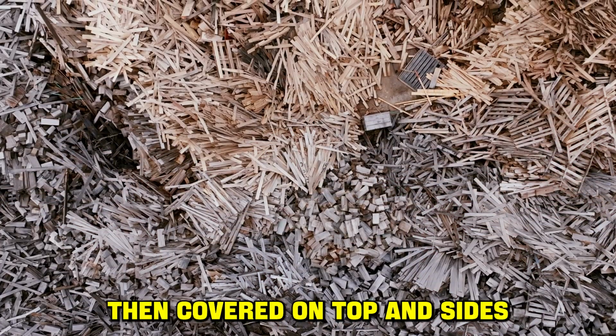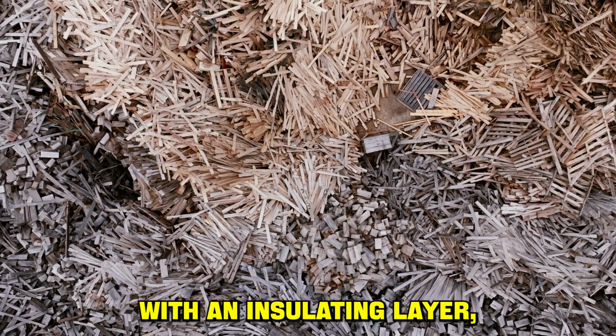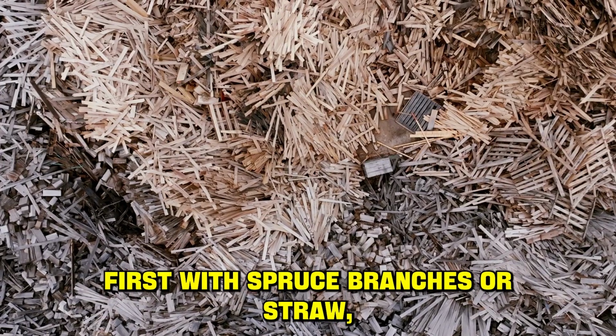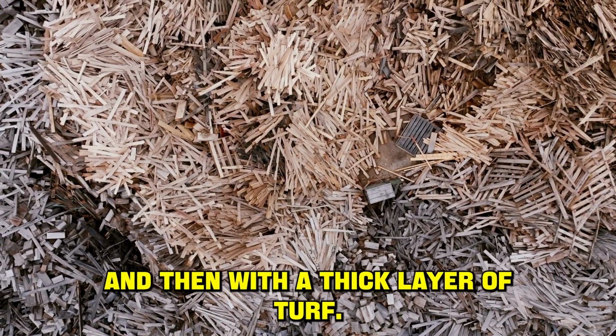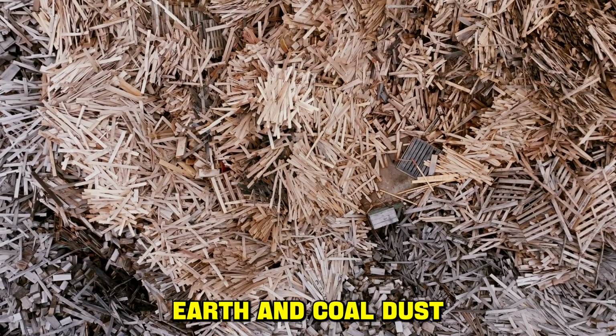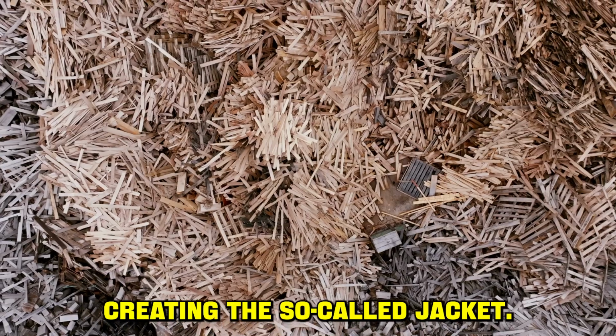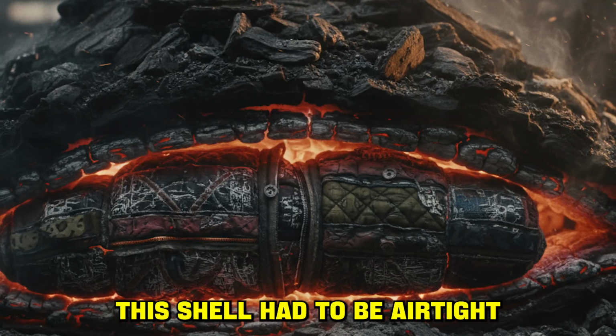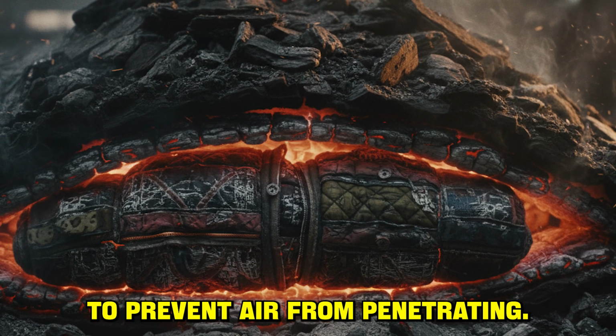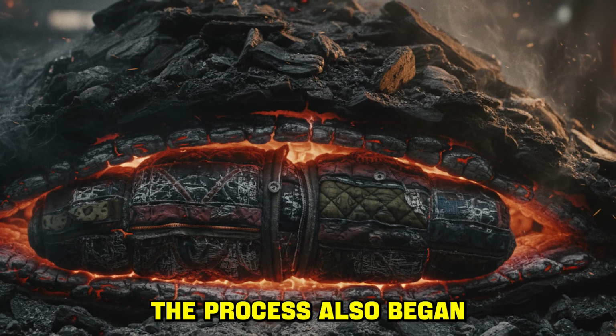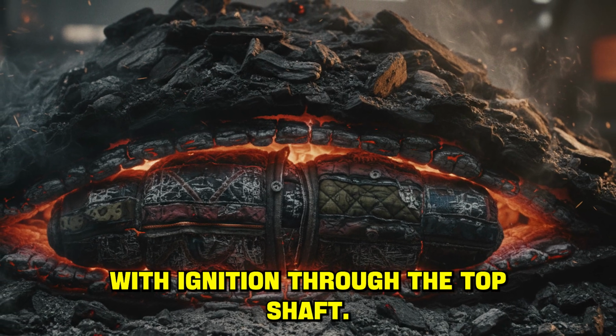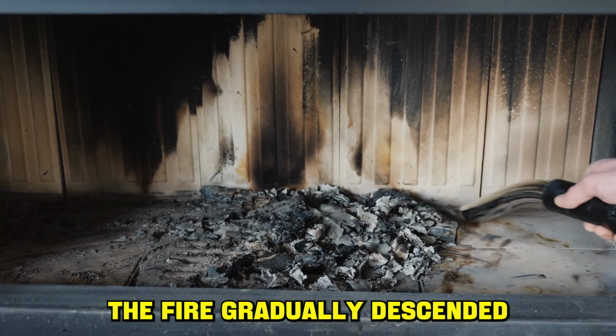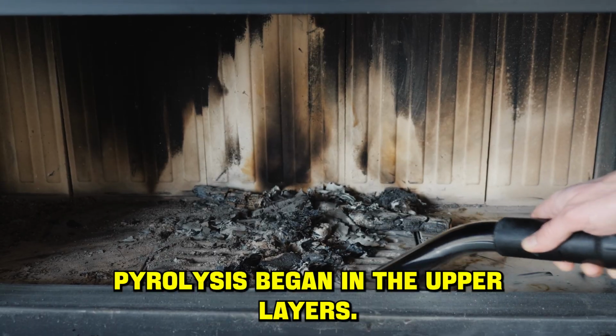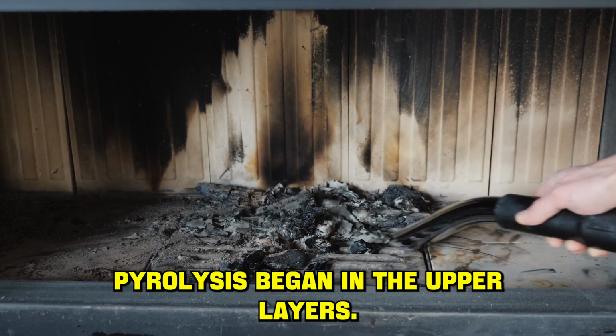The pile was then covered on top and sides with an insulating layer, first with spruce branches or straw, and then with a thick layer of turf, earth, and coal dust, creating the so-called jacket. This shell had to be airtight to prevent air from penetrating. The process also began with ignition through the top shaft. The fire gradually descended, and as it moved, pyrolysis began in the upper layers.